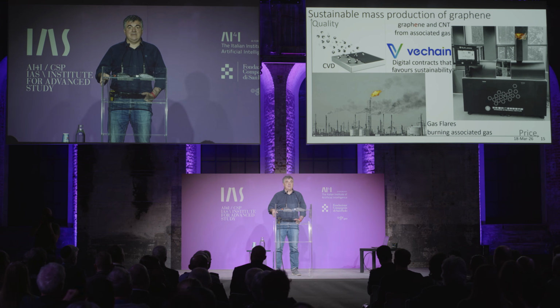And it's becoming even more relevant because lots of companies, especially in the countries which are rich in oil, are looking into the opportunity of how to burn oil without emitting CO2, and they basically create turquoise hydrogen by cracking oil or carbon-containing gas into hydrogen and carbon. And for them, it's really important to make this carbon functional, otherwise they lose about 30% of their revenue. When you burn your hydrocarbons, 70% comes from burning hydrogen, 30% comes from burning carbon.